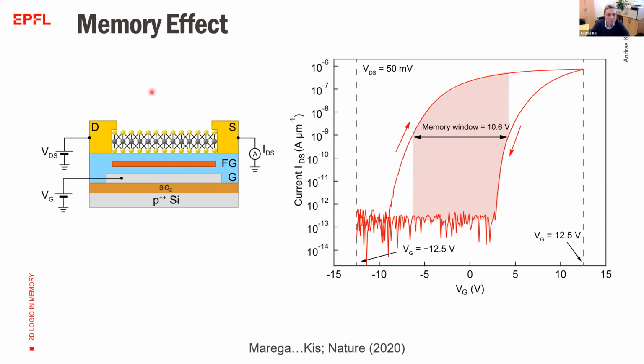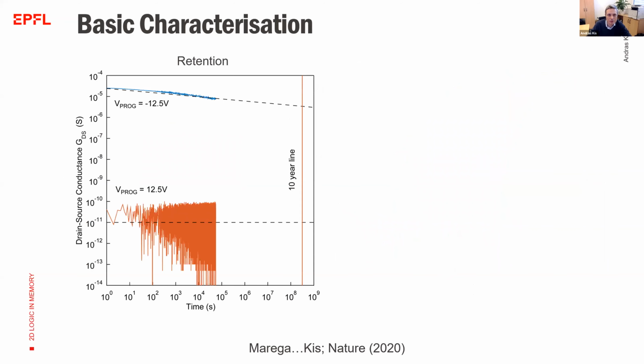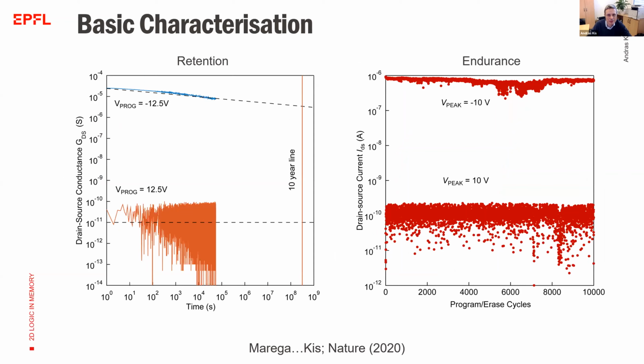So now the memory effect and the storage of data can be seen if we sweep this gate voltage and we look at the current in the device. So then we get this hysteresis, which is coming from the fact that your charges, depending on the voltage configuration, can be stored or released from this floating gate, and that influences the threshold voltage of the transistors. And then if we perform just the basic characterization of these memory elements, we see that we can in principle extrapolate to something on the order of 10-year retention for 2 memory states, and the devices themselves can survive at least 10,000 cycles of switching and erasing.